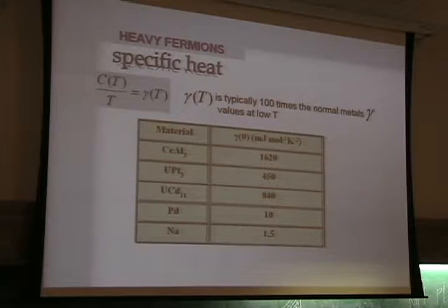But in heavy fermions, the specific heat is typically 100 or 1,000 times that observed in normal metals. And it also keeps varying with temperature. You see here some examples. This is the best-known example of a heavy fermion material. And you see how big gamma is going to zero temperature. This can be more than 1,000 times that of palladium and sodium materials.